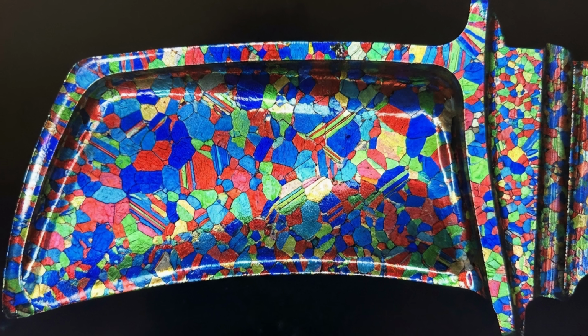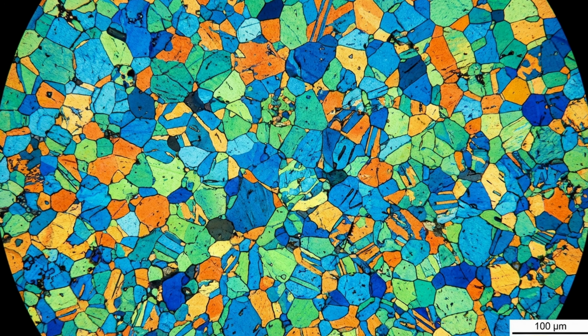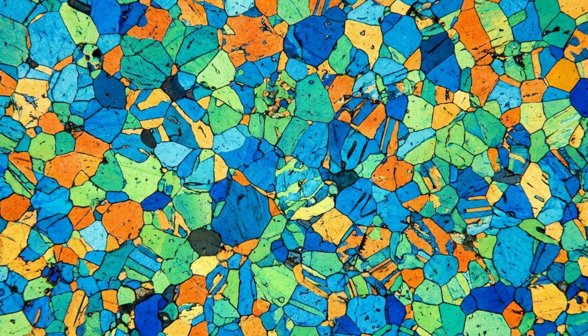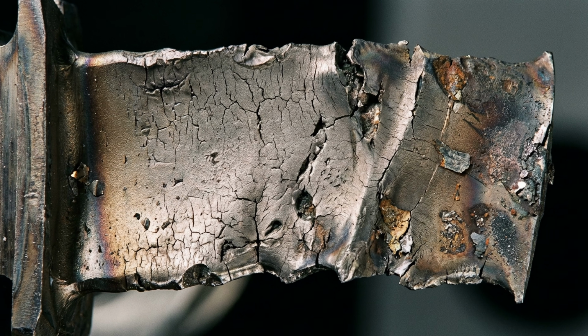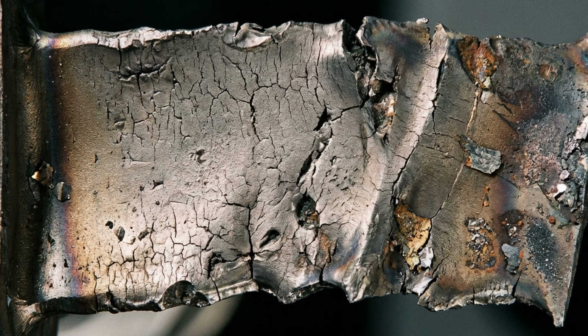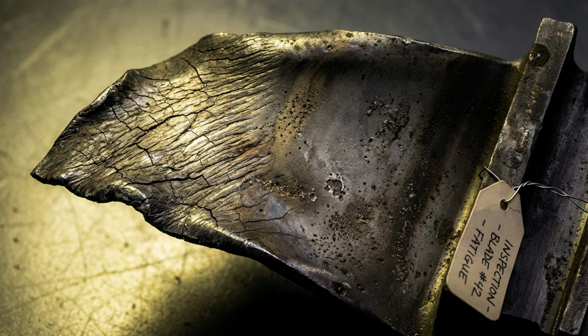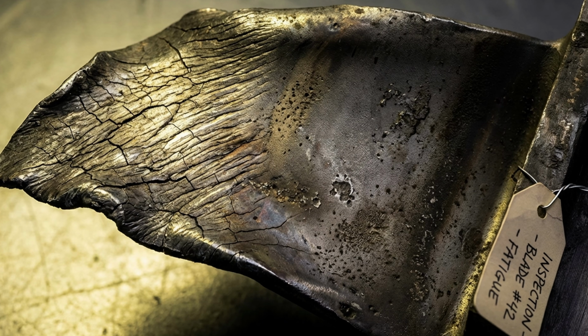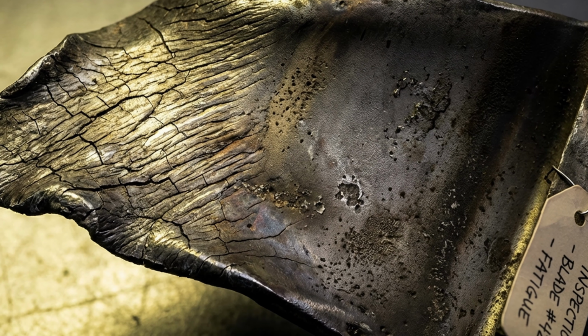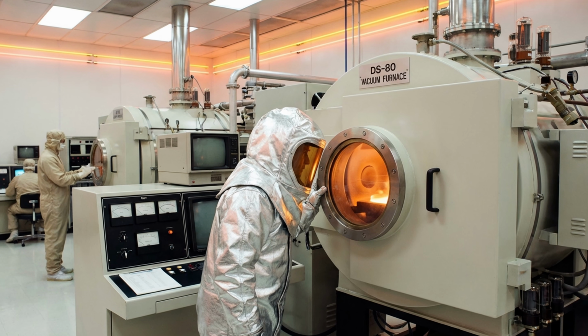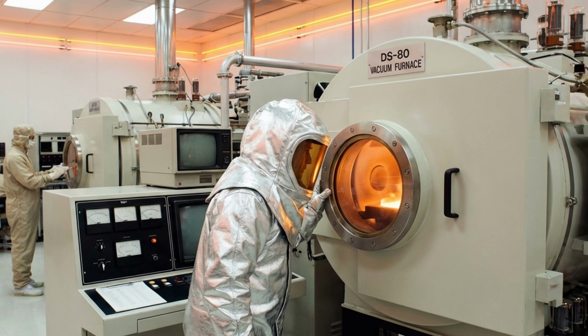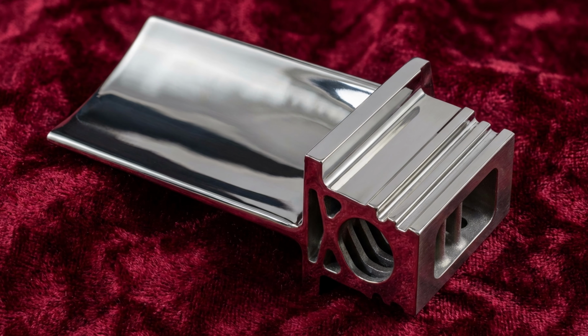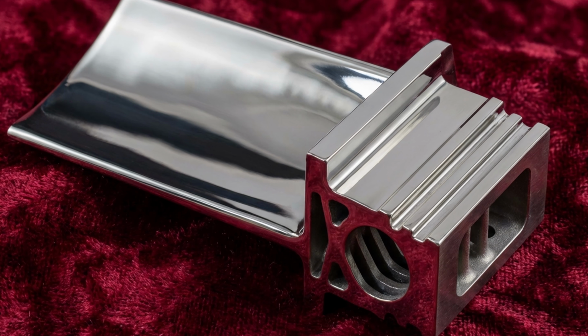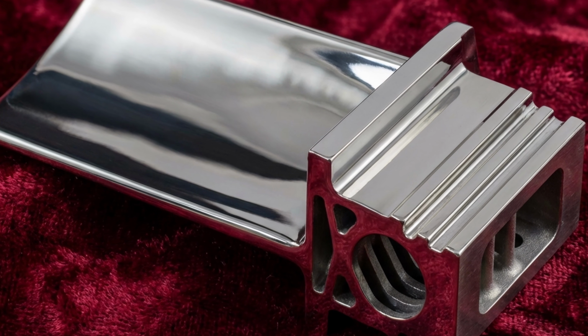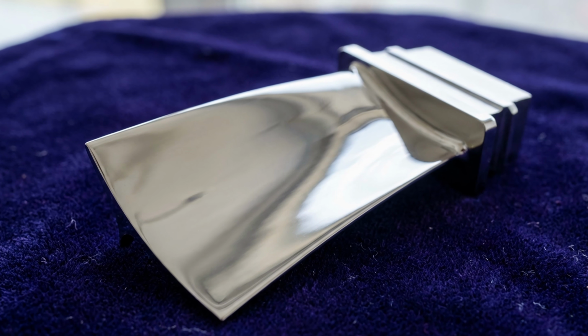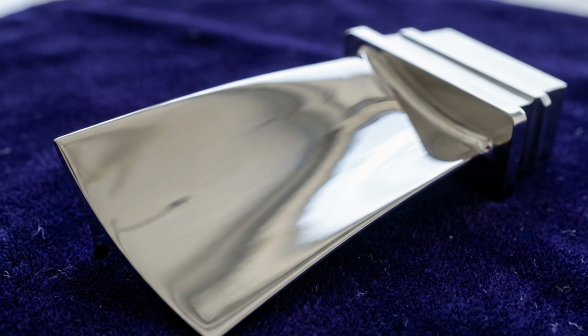Traditionally cast turbine blades are polycrystalline, meaning they comprise a microscopic three-dimensional mosaic of varying metal crystals or grains formed during solidification in the mold. Under extreme heat and continuous centrifugal stress, the boundaries between these microscopic grains become intensely vulnerable to a phenomenon known as creep deformation, where the metal slowly stretches, deforms, and eventually fails. Beginning in the later decades of the 20th century, aerospace companies perfected directional solidification and ultimately single crystal casting. By meticulously controlling the cooling process to entirely eliminate grain boundaries within the airfoil, single crystal blades exhibit up to 9 times the relative lifespan for creep strength and thermal fatigue resistance compared to their older polycrystalline counterparts.